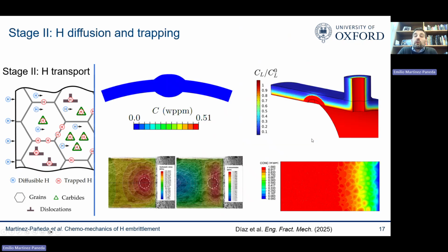Basically, you can implement that equation into your favorite finite element package. And when you do that, you can simulate any boundary value problem and see how the hydrogen distributes. For example, here, this is a pipeline with a weld. You see how the hydrogen diffuses through the pipeline. This is a pressure vessel, microstructure, any geometry that you're interested in, you're able to predict the distribution of hydrogen in time and space. But this is only part of the picture.